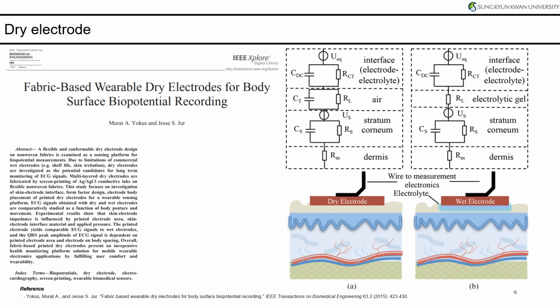research in this area. First, to obtain stable EP signals for a long period of time, dry electrodes should be used instead of wet electrodes. Wet electrodes have the advantage of conformal contact with the skin, but the gel becomes dry, the electrode characteristics change, and rash or skin irritation can occur, making them unsuitable for long-term use. In this paper, they used a fabric-based wearable electrode as the dry electrode to record biopotential signals.